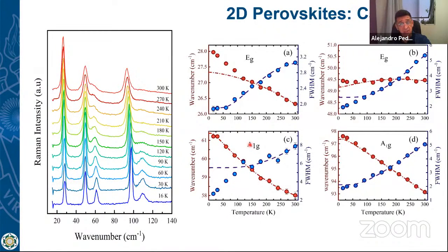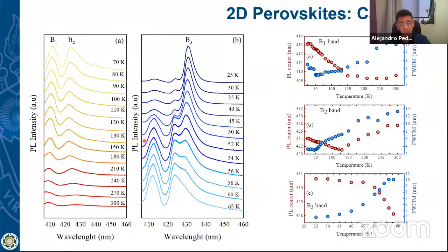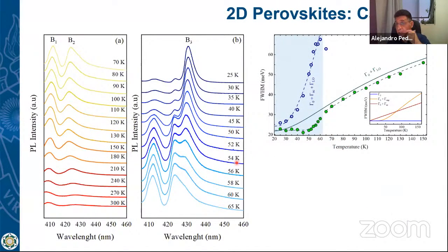And when we study the luminescence, which is maybe the most important property here, you can see what was previously reported. The luminescence is increasing down to liquid nitrogen temperature, but when we go below liquid nitrogen, new bands appear much stronger than the original one. And when we investigate how these bands change as a function of the temperature, we can describe this behavior as an exciton-phonon coupling.